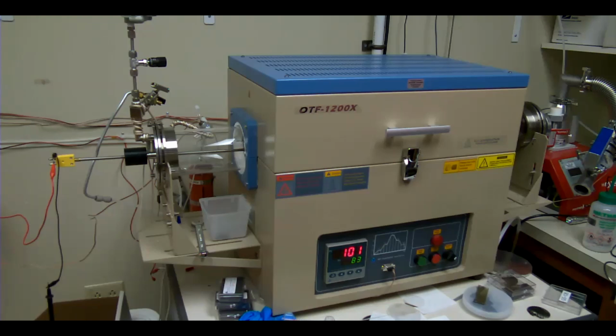probably sometime on Friday or the weekend I'll come and take it out, and then we'll remove the excess boron on the surface, etching it away in BOE, buffered oxide etch, and also remove the PECVD oxide. We don't need that anymore, so we can take it all off. And then what I'm going to do after that is flip the wafer and dope the backside. I have a phosphorus oxide source, and I'll use that to dope the backside.